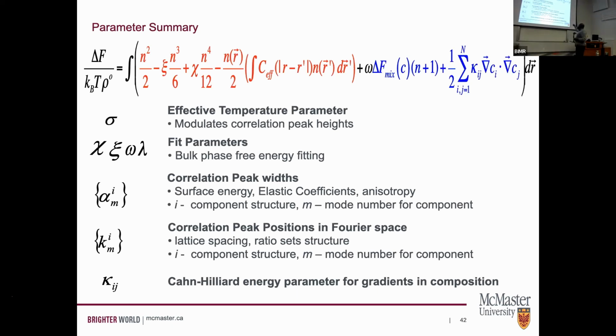It turns out that this particular model could also be motivated from a more fundamental theory, in this case, classical density functional theory. I won't get into that, but when you do and you construct a full free energy functional that includes composition, density, you get a set of parameters that all modulate something physical. So I get something that modulates peak heights, temperature. Essentially those periodic peaks, I could think of them as pseudo-atomic positions. And so modulating those peak heights is like modulating temperature. I get things that could fit to some bulk phase or energy description. I get a bunch of terms that link to elasticity, surfaces. And I get terms that tell me about the structures that I aim to create with this method. And I get things that tell me about solid interactions between two different elements. Okay.